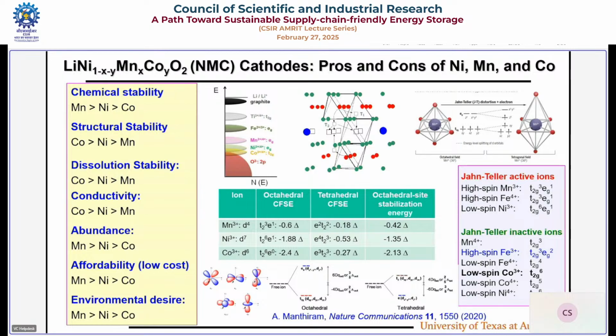So they are split. 3 of them are down, the ones that go in between the axes. Once they are along the axes, it's up. That's called crystal field splitting. Electrons will distribute here and there. So based on that, you can calculate what is the crystal field stabilization energy. For example, if you have 3 electrons, I will have 1 here, 1 here, 1 here. But if it is splitting, then those 3 electrons will be at a lower energy. So the system gains more stability. So that is what is called crystal field stabilization energy in the octahedral site. Tetrahedral splitting will be exactly opposite.